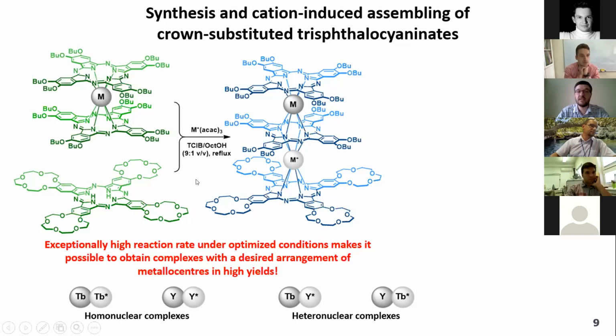It is a mixture of trichlorobenzene and octanol in the magic ratio of 9:1. Exactly in this mixture, it takes 8 minutes to reflux the reaction mixture to form this complex, and one simple chromatography to isolate it in a pure form. Moreover, this very rapid reaction rate allowed us to avoid any possible scrambling with formation of other combinations of lanthanides and ligands, and thus we succeeded to synthesize series of homonuclear complexes, for example, containing 2 terbium ions in these positions, and heteronuclear complexes which contain either terbium or yttrium in different positions.